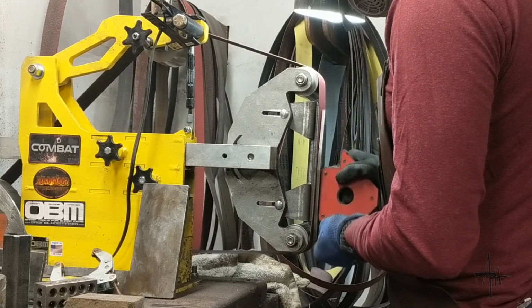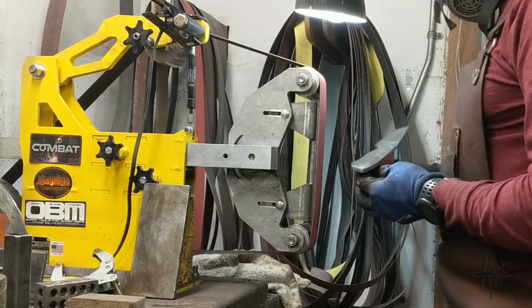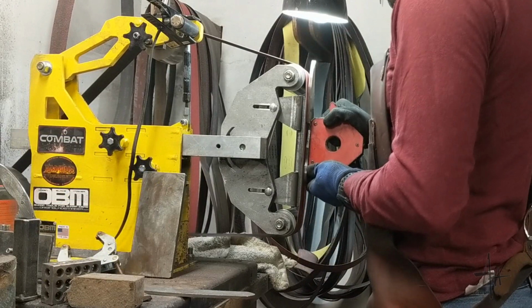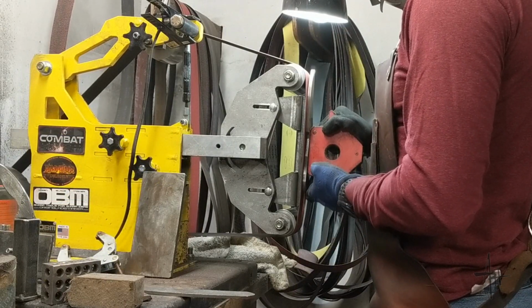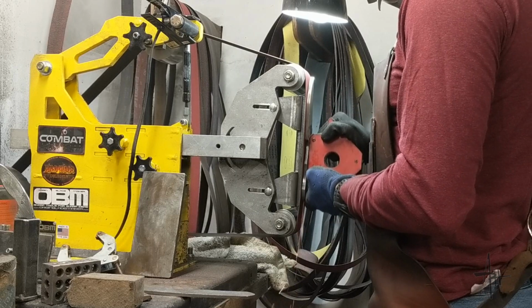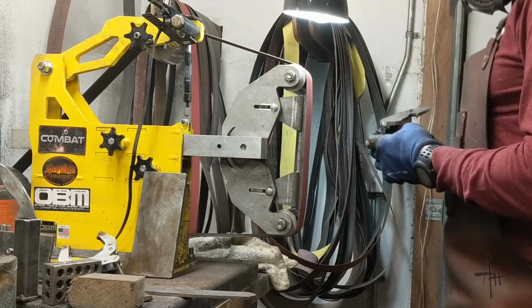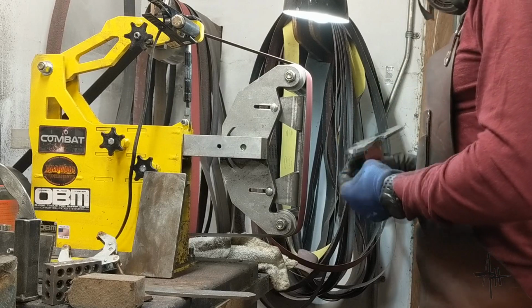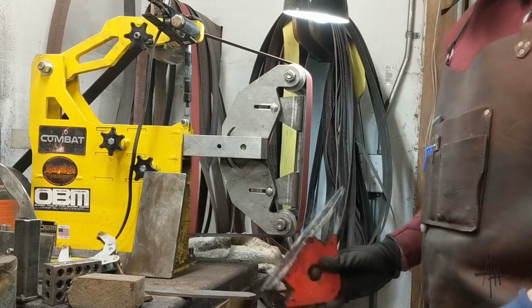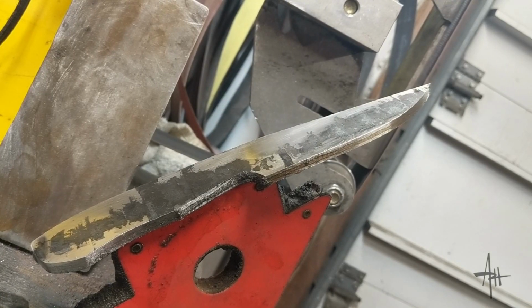Once your blade is profiled, it's time to take it to the grinder and flat off the sides. Now, it's very, very important that you first take your billet to the tempering oven and anneal it in some way to make that stainless steel a little bit softer. You won't be able to drill through it if you don't, and it is a total pain to grind if you don't anneal it first.